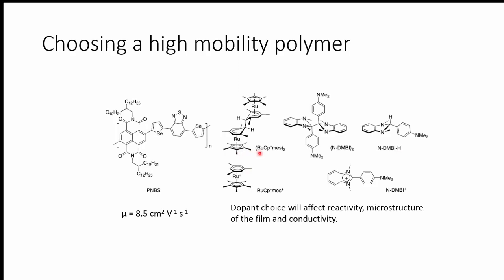So for example, this ruthenium dimer, upon reaction, it will give this ruthenium-ruthenium-based cation. However, this cation has a large volume. So it will have a hard time being innocent inside the film and not distracting the polymer chains from stacking properly on top of each other. Versus if you have these N-DMBI based compounds, the cation is more planar, although it is the same size technically, but it is less bulky, so it can go wherever it wants without being a problem. That at least was our hypothesis when we first started this.